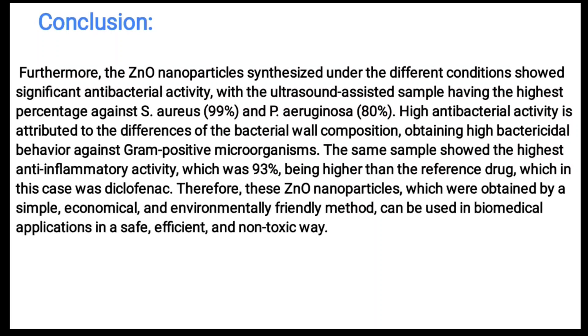In conclusion, zinc oxide nanoparticles synthesized under different conditions show significant antibacterial activity, with the ultrasound-assisted sample having the highest percentage against Staphylococcus aureus at 99% and P. aeruginosa at 80%. High antibacterial activity is attributed to differences in bacterial wall composition, obtaining high antibacterial behavior against gram-positive microorganisms. The same sample showed the highest anti-inflammatory activity at 93%, being higher than the reference drug diclofenac. Therefore, these zinc oxide nanoparticles, obtained by a simple, economical and environmentally friendly method, can be used in biomedical applications in a safe, efficient and non-toxic way.